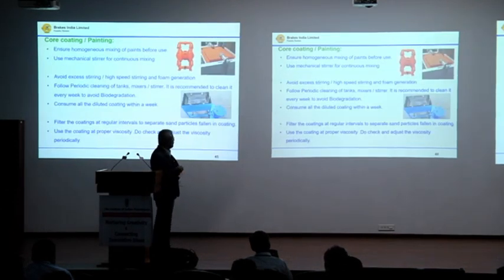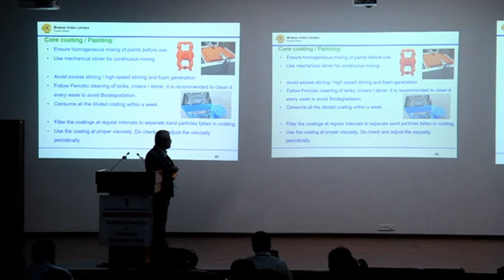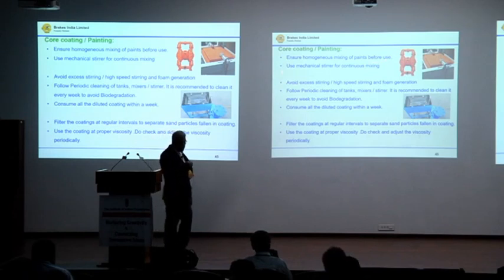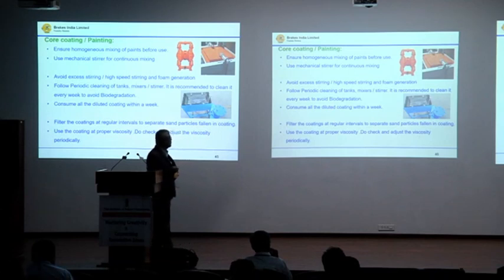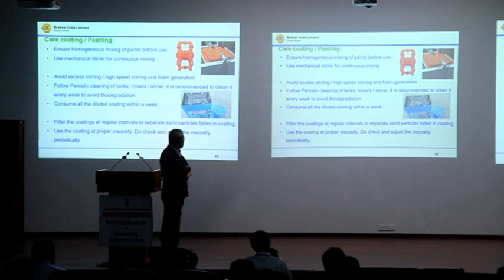This is the core coating and painting parameters. Ensure homogeneous mixing of the paint before use, because it contains a lot of liquids which uniformly have to mix to have better performance. Use mechanical stirring for continuous mixing, and avoid excess stirring, high-speed stirring, and foam generation.